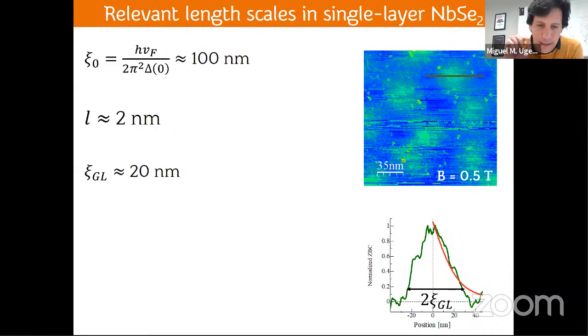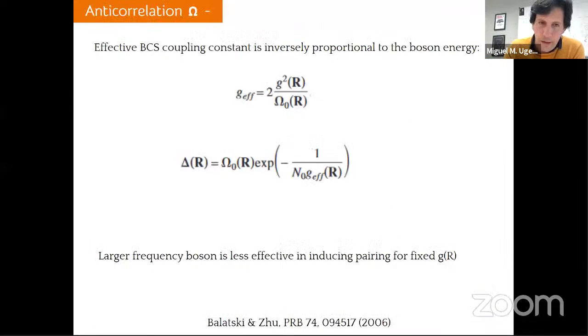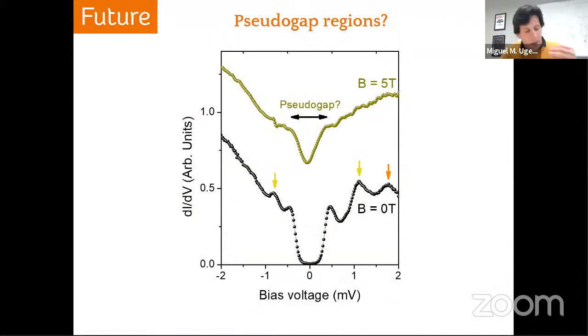The second part of the explanation is that when you go above the critical field, in general, not always, what we observe is a V shape in the density of states. In the normal state, we see a V shape. We don't know the origin of this dip. One of the options could be a pseudogap, or it's just a dip due to electron-electron interactions. So we don't know that.